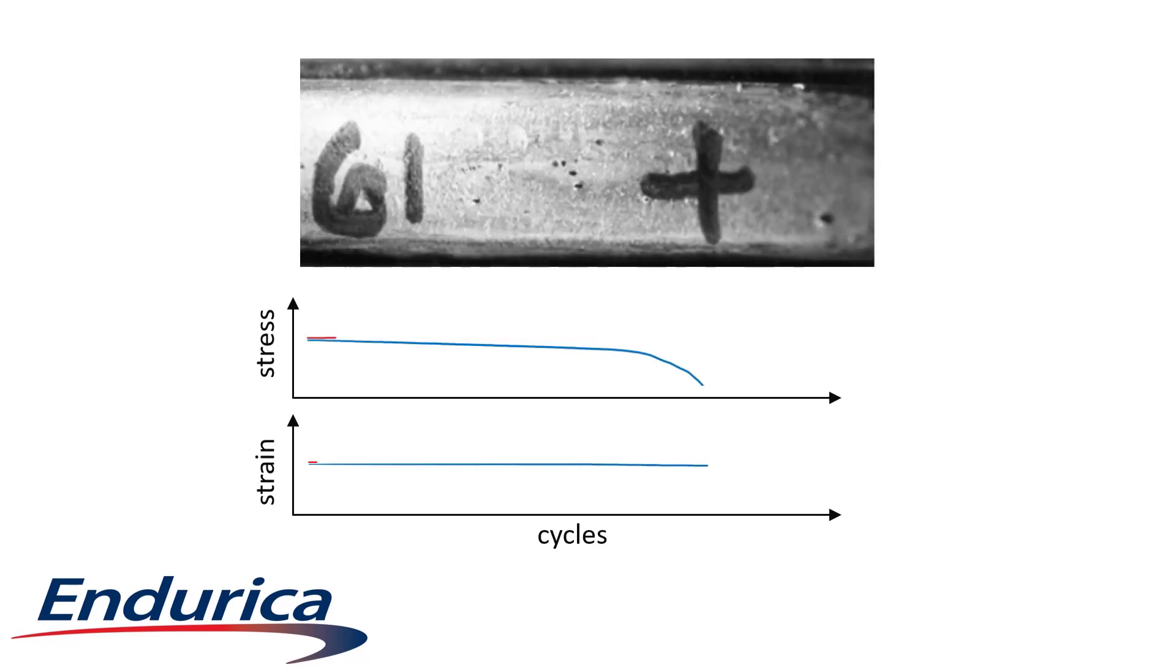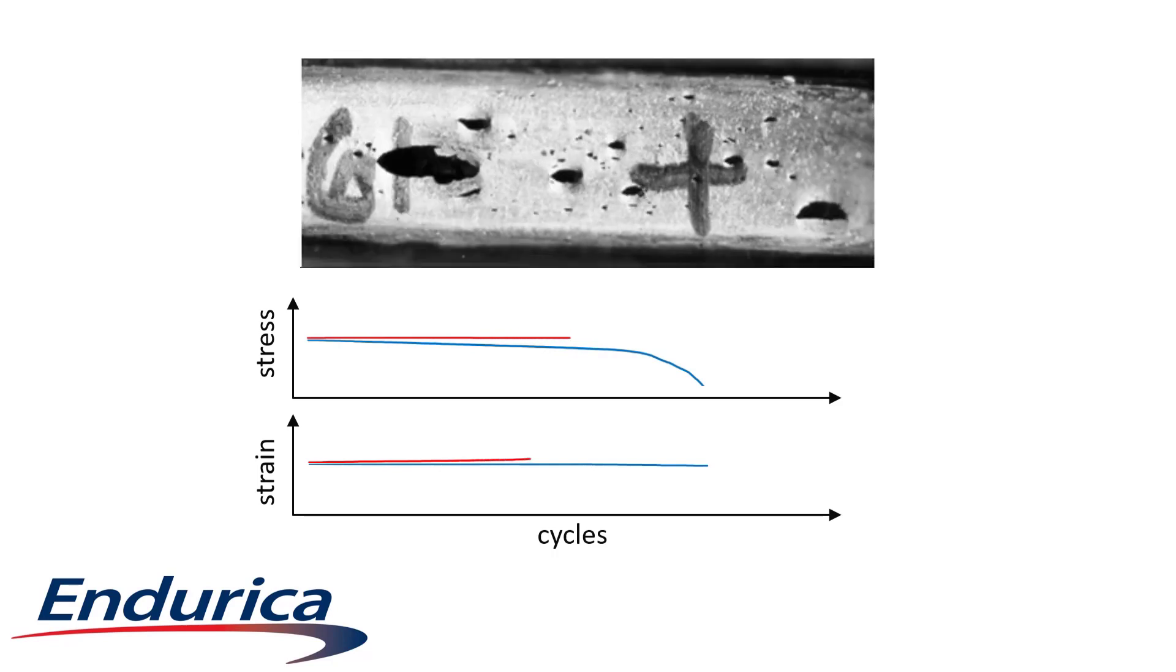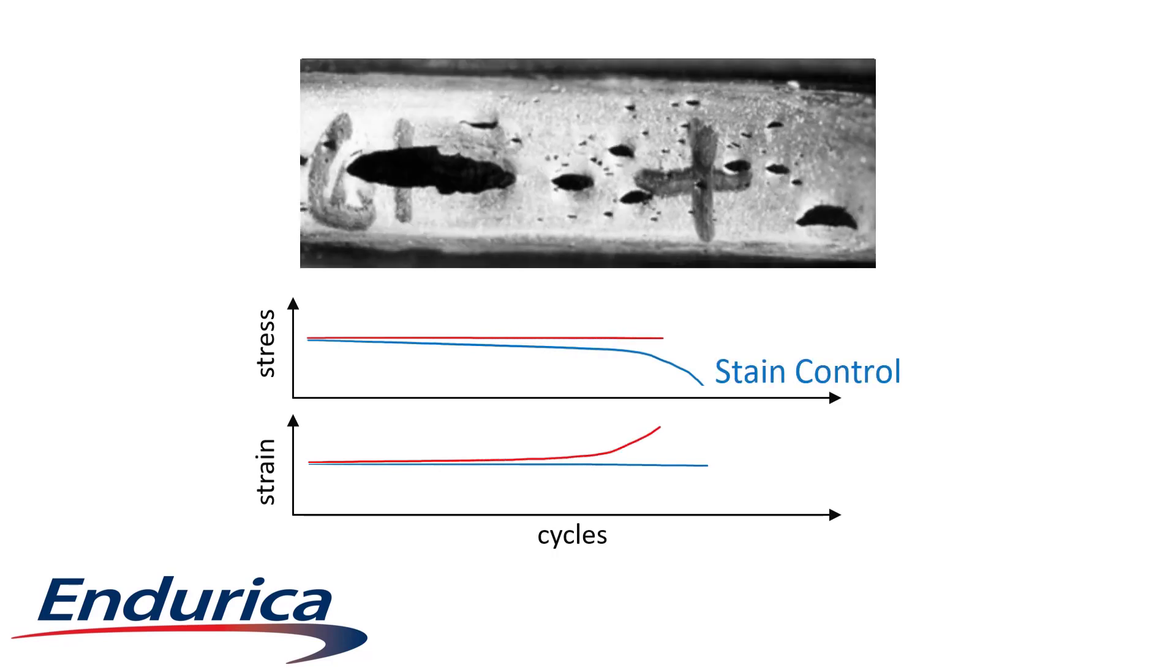Stiffness loss is critical in situations where the mode of control might change. Fatigue tests run in strain control and in stress control will give different fatigue lives even when they start out from the same operating condition.